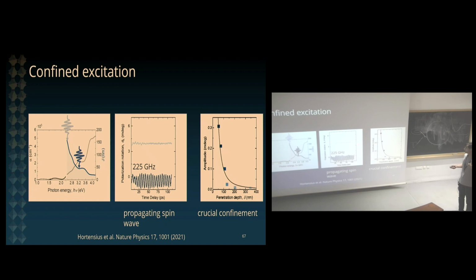What I would also like to stress is the importance of this penetration depth being very short. So here I'm showing the detection of the propagating mode done by exciting the system in a range in which the penetration depth is very small, and by exciting the system in a range where the penetration depth is 3 times larger. Okay, and you see that if the penetration depth is large, you detect no propagating mode whatsoever, while you have a well-defined propagating mode if you satisfy this condition: penetration depth way below the wavelengths. And these are various data points measured for different sizes of the penetration depth. So confinement is really fundamental to have a propagating mode.